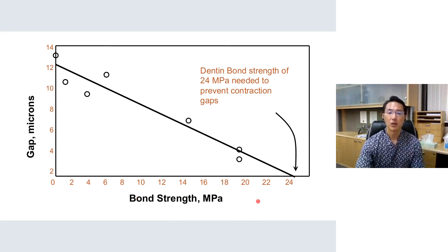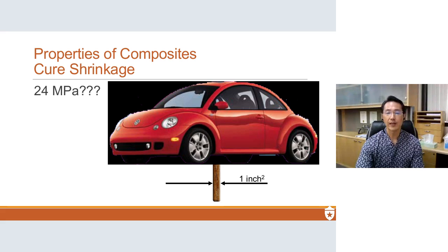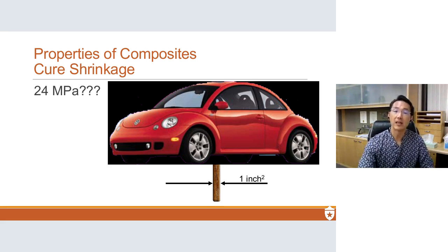Okay, 24 megapascals. So you're probably thinking, what does that mean? What's the big deal? It's just that 24 megapascals is equivalent to a 3,000 pound beetle on top of a 1-inch square thick stick. That is the stress being generated by a shrinking composite. That's huge, right? Now, manufacturers actually have developed bonding agents that have higher than 24 megapascal bond strength. But other problems start to arise.